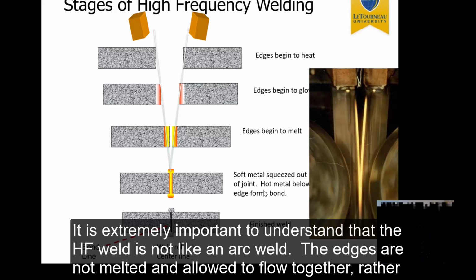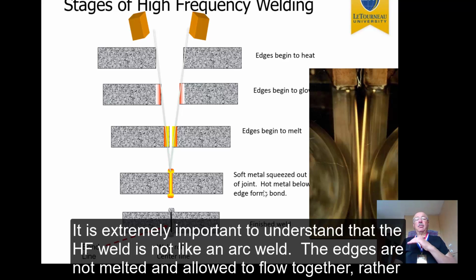At the end, by the way, the excess material is shaved off. We call that scarfing. And this can happen very fast. Small tube welding can go practically at sometimes hundreds of feet per minute, but then oil country tubular 10-inch diameter steel at maybe half-inch wall thickness can weld at 70 feet per minute. In any case, this happens very fast. And that really produces millions of miles of weld since they invented it.